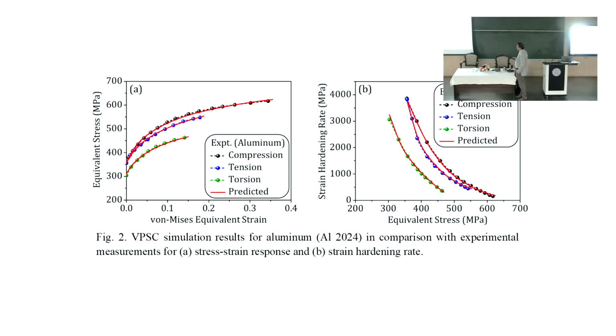But now we are doing real business, because the simulation is on the polycrystal, and you do not only get this result from the VPSC. This is not the only result, it's just some part of it. With the VPSC polycrystal model, you also get, for example, grain shapes, crystallographic texture, orientation distribution, and it's measurable experimentally, you can compare. That also has to agree with the experiment. So many more results are coming out. This is just one part of it, but this is one application possible of the VPSC model.